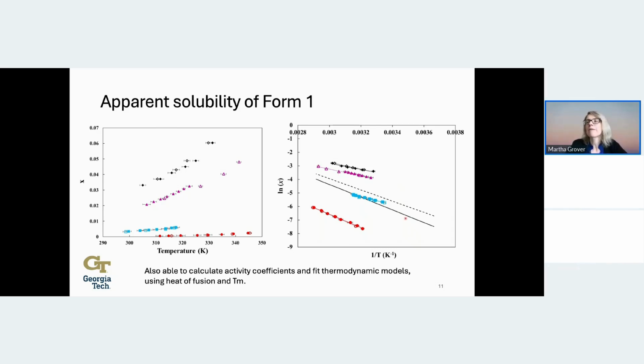And then we also have the ideal limit associated with having an ideal solution. And so we can calculate that from just the heat of fusion that we got from the DSC as well as the melting temperature. And then we can compare where acetone is relatively near that kind of ideal situation, but acetonitrile is really much more favoring crystallization and phase separation. So we were able to do some additional thermodynamic modeling that you could read about more in the paper if you're interested.